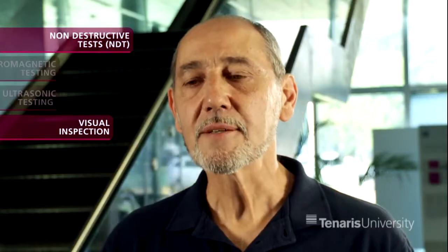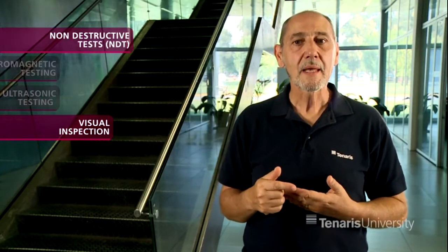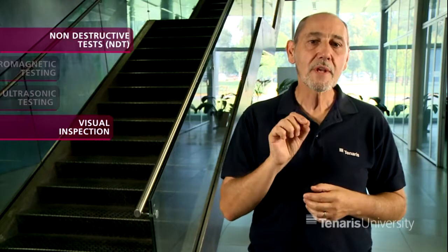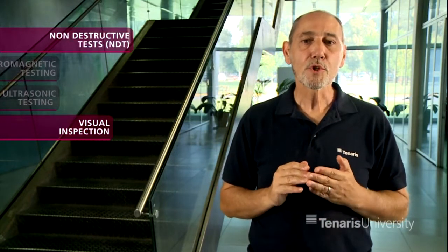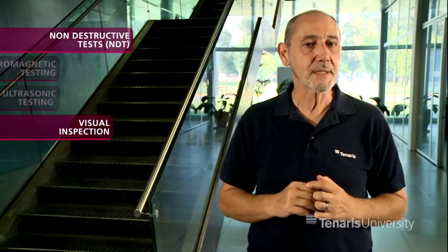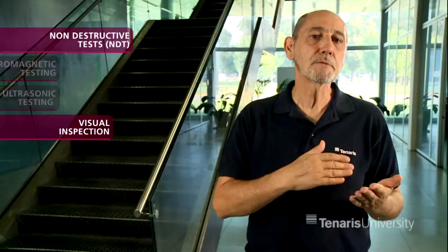Any defect found by any means is removed by grinding, and then the remaining wall thickness is controlled to ensure that it is still within the specified wall thickness tolerance. If the defects can be removed, then the tube is re-inspected. Otherwise, it is rejected.